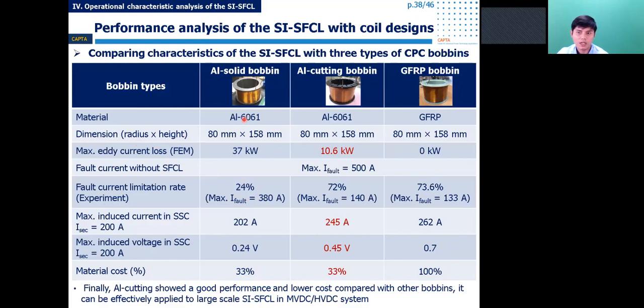This slide summarizes and compares the characteristics of the SI-SFCL with the three kinds of CPC bobbin. In detail, you can see the aluminum cutting bobbin not only has good performance similar to the GFRP bobbin, but also significantly reduces the induced current and voltage in the secondary coil. Especially, it has a much lower cost. So this bobbin type is the most effective to use in the practical SFCL design.